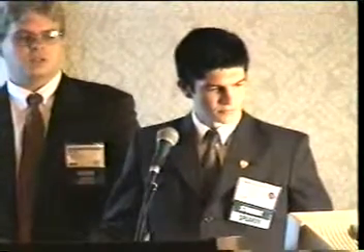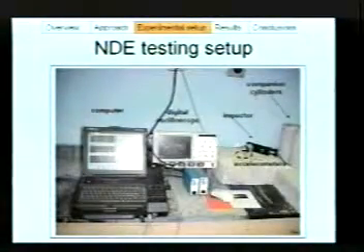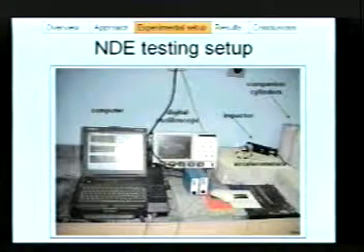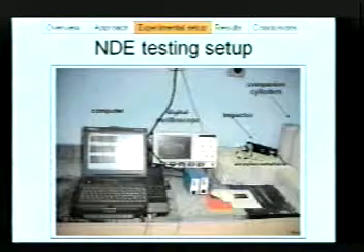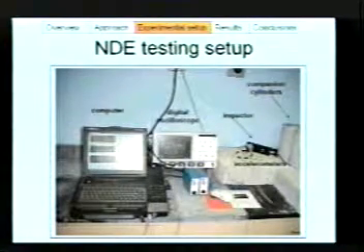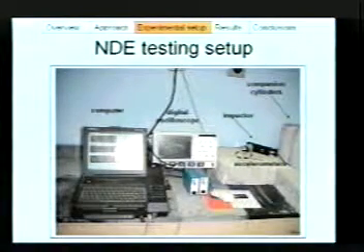Okay, any other questions? Sure, Pete. I wondered, in one slide, you showed the companion cylinders for the slabs. Is that how you determined your compressive strength for the slab, from those companion cylinders? Yes, we cast 3 companion cylinders to be tested at each time. If you recall, we did compressive strengths at 7, 14, and 28 days. So for each measurement, we had 3 companion cylinders that were tested, and like that, we determined the compressive strength. On exactly the same day that we did the compressive strength, we took the NDT measurements, so we have complete correlation with the data.